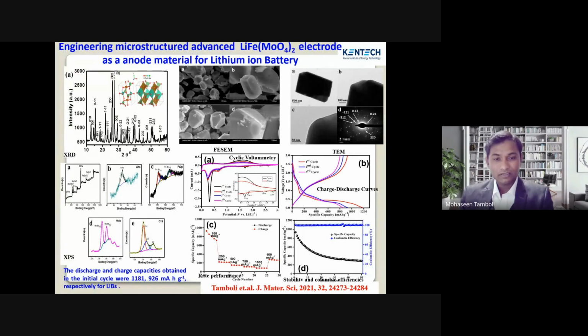When we check the stability of our material even after 25 or 50 cycles, it shows the same consistent results and good stability compared to the sodium iron molybdate lithium ion battery results. And in figure C, it shows different current densities. We have checked our material at different current densities, and it also shows the same consistent results with high specific capacity.